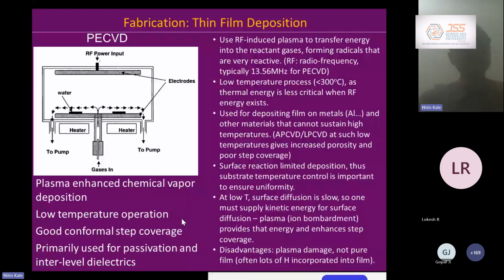You are going to get the gases into a chamber, and then you are going to apply an RF power. You are going to apply an electric field. Using the electric field, you will dissociate the source gases. Say silane becomes Si and H, ammonia becomes N and H, and then the Si and N can react, and that film is going to deposit on your substrate. So that is plasma enhanced CVD.